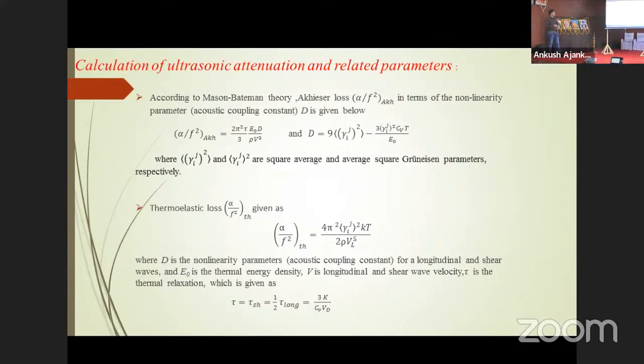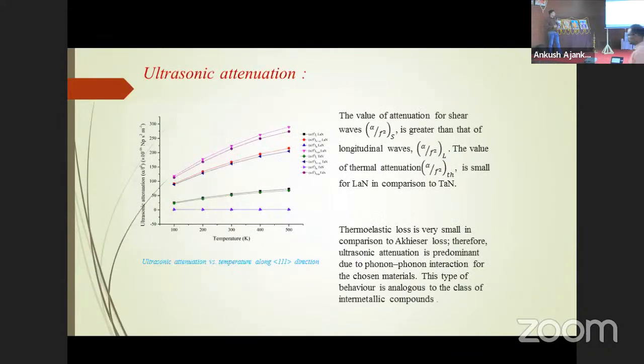And the formula for the evaluation of thermoelastic loss and phonon-phonon loss is given here. With the help of Mason-Bateman theory, we evaluate the loss. In the slide, the total ultrasonic attenuation has been plotted with varying temperature, and it is clear that thermoelastic loss is very small in comparison to the phonon-phonon loss. Therefore, ultrasonic attenuation is predominantly due to phonon-phonon interaction.